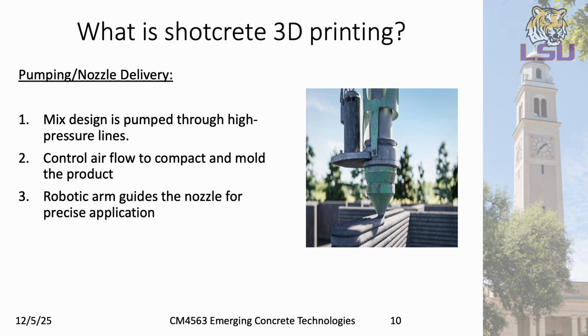The nozzle uses airflow to shape and compact the spray pattern, improving density and interlayer adhesion. Standoff distance, spray angle, and travel speed are precisely controlled by the robotic arm to maintain consistent dimensions and geometry. Because the shotcrete is projected at high velocity, it self-compacts on impact, eliminating the need for any vibratory tools. This stage directly influences density, bond strength, surface quality, and the finished structural performance.